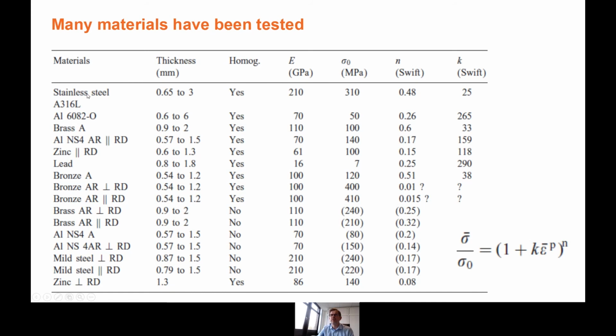I will not go into details, different thicknesses. And here you see the flow properties of the material, and the hardening law that we use is a so-called Swift hardening law with strain hardening exponent n, where sigma 0 is yield stress and K is a hardening coefficient. All right.